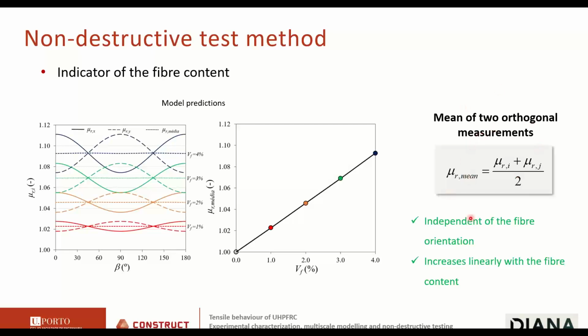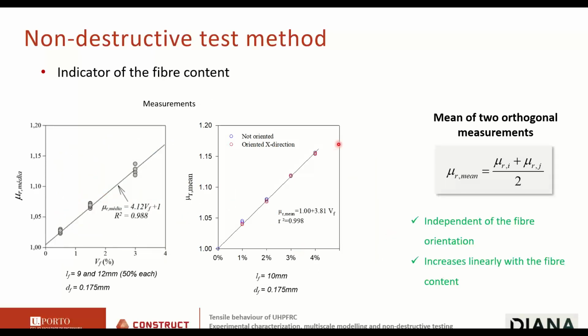So a good indicator of the fiber content is the mean of two orthogonal values, and it can be shown that it's independent of the fiber orientation, and good news, it increases linearly with the fiber content. And we confirm this with the measurements. It increases linearly with the fiber content.